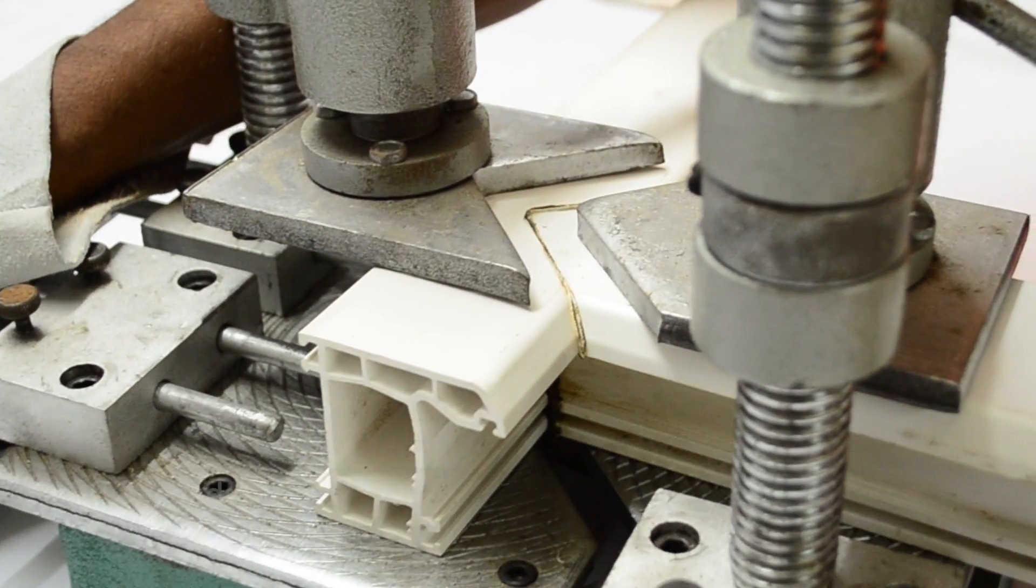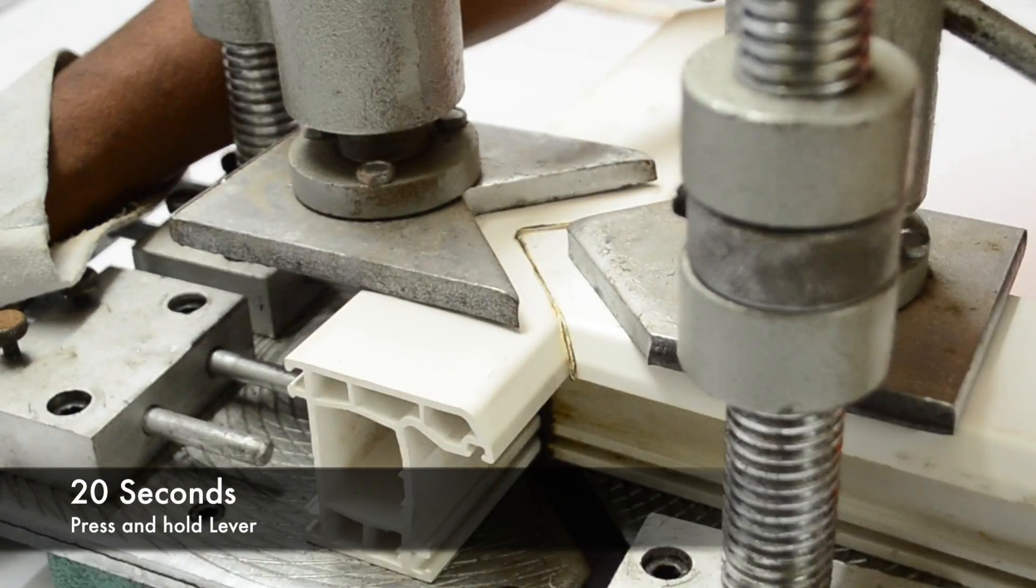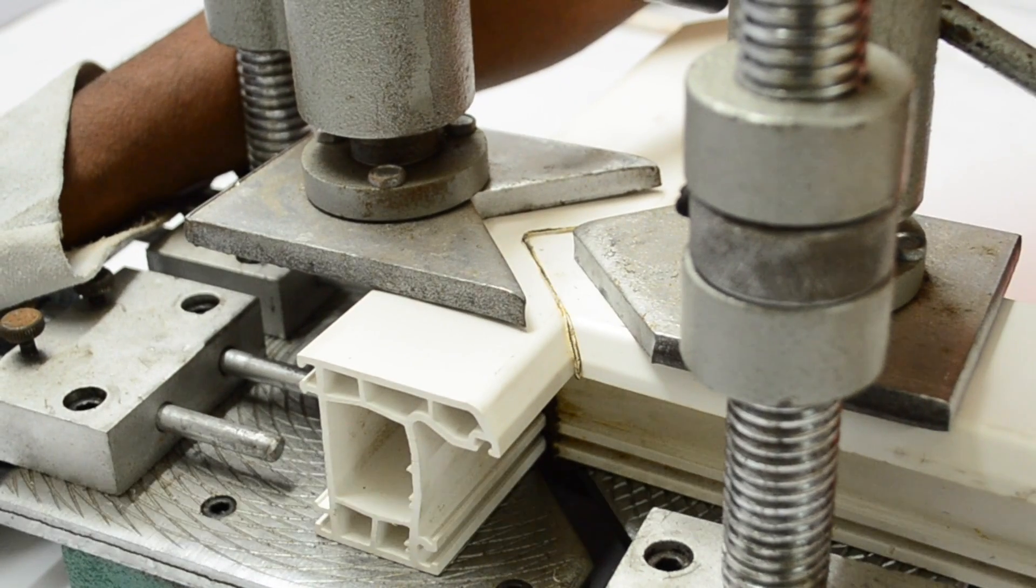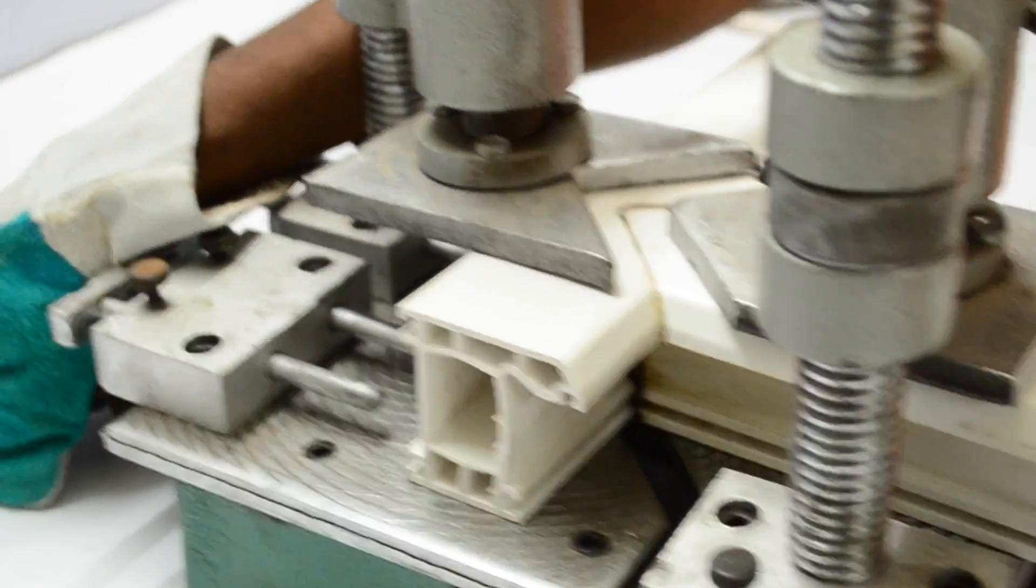After 20 seconds, the edges of the profile will start to melt. Press together the profiles using the same lever for 20 more seconds.